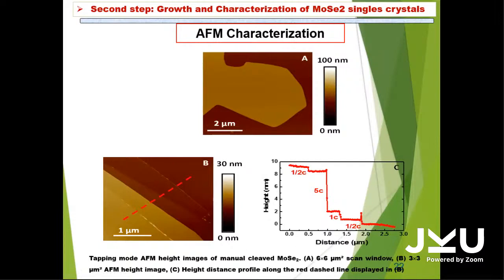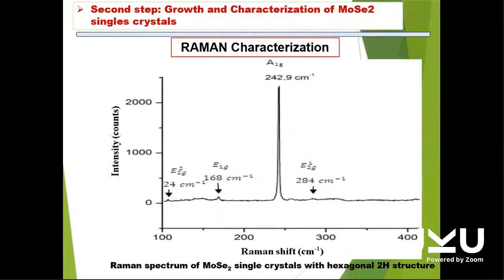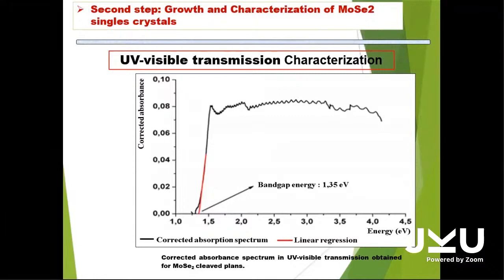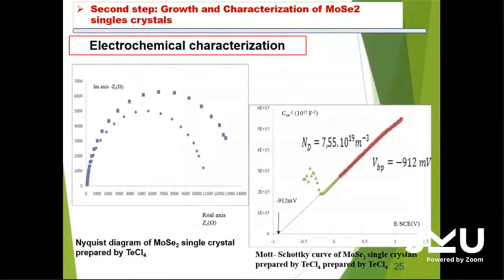After this physical characterization, the electronic properties of the materials were identified. UV spectroscopy was used to identify the band gap energy of these materials, and the value obtained is in agreement with what was found in the literature. After this, we used other types of electrochemical analysis, such as Mott-Schottky curves, which help us to identify the flat band and the carrier density of the materials. All of these results show that our materials are in good condition.